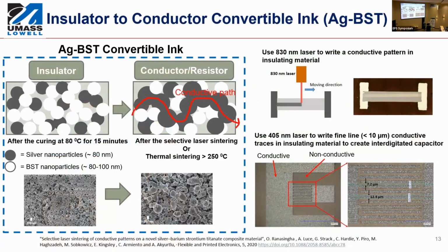Another ink that we have was actually developed by one of our faculty members, Dr. Ash Ranasinghe, who's here. So resistive inks is also another area that needs more research when you're going into printable electronics. So the idea here is taking conducting ink, the commercial silver ink, and then putting BST nanoparticles in it to make it more resistive, essentially. So this is called the AGBST ink. The beauty is when you put it on, it's an insulator. But then when you either thermally cure it, or you can actually go in and laser sinter it.